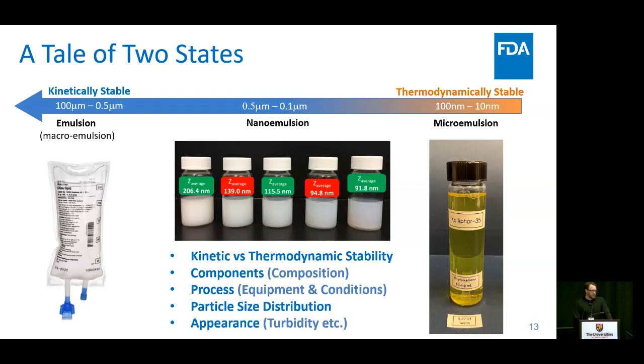So both like the turbidity here, the optical properties, as well as the drug distribution, where the drug actually is in the product. And so for the thermodynamically stable system, we're usually in that kind of micelle size range, the 10 to 100 nanometers, and it goes up for these kinetically stable systems. And of course, the turbidity is a big giveaway here that something's an emulsion versus being an isotropically translucent material.